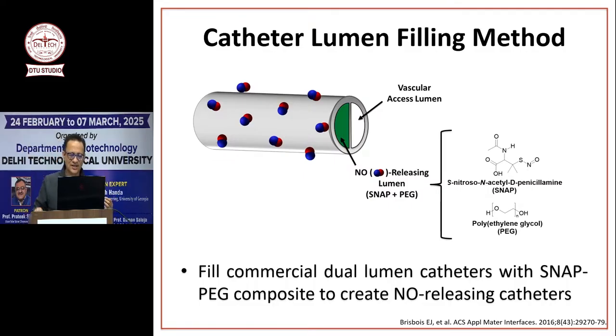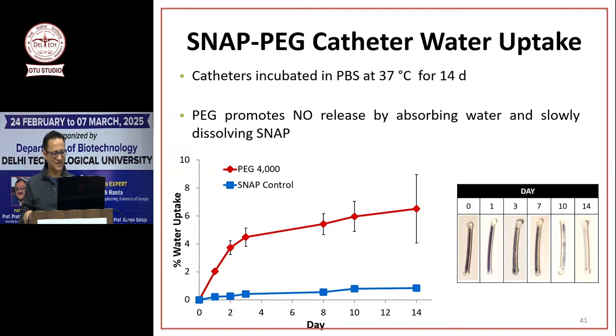This is just an idea. We wanted to show it, instead of in a lumen, we made catheters, filled NO donor in them, and showed that when we just fill SNAP powder in that lumen, we get a very low NO release. But if we fill PEG, which is a hydrogel, with NO donor, we get a really good NO release because it's a moisture environment and the hydrogel is helping NO to break and release.